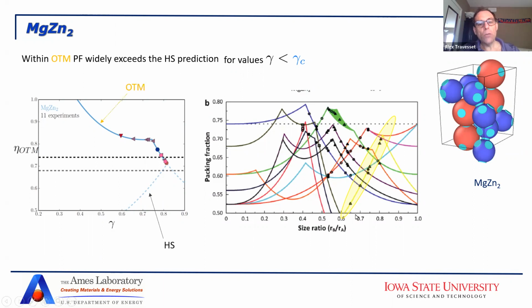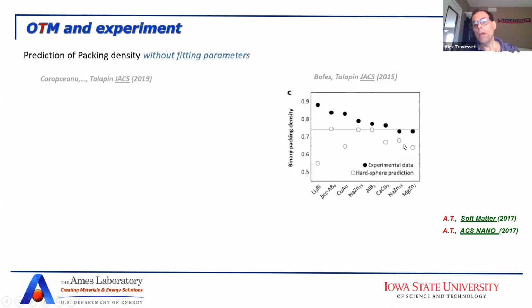Now, the next thing we can do is go and look at this plot. Here what we have is the hard sphere prediction. Here is the experimental data, and then when we compute the new packing density, and there are no fitting parameters here, everything is determined, we get the result where we are able to exactly match what the experiment says, except for one point. And when I got this, I immediately contacted Dimitri Talapin and Michael Boles, and I said, look, I have a problem with gold copper. Do you know what is happening here?